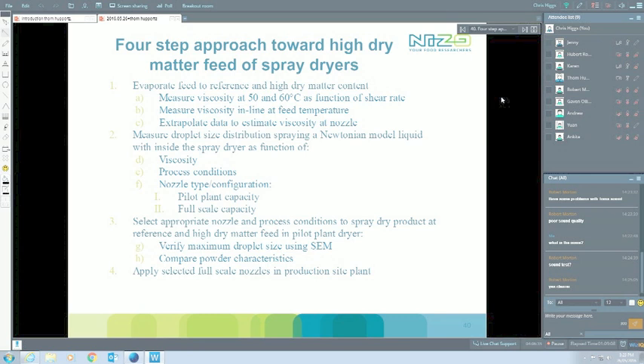You can get that higher dry matter, but you need to know how that product is going to behave when it gets into the dryer itself and it's being atomized there. That was really about, okay, what viscosity will it have? Because that's one of the key ones. Can we extrapolate that as well, of course, to what it actually has in the dryer? Because shear rates in the atomizer in a dryer are in the order of 10,000, 100,000 per second, and that's something we can never measure in a lab properly. On the other hand, of course, temperatures are going to be higher as well during atomization in the dryer than what we can safely and typically measure in the lab. So we need to be sure that we can extrapolate that.